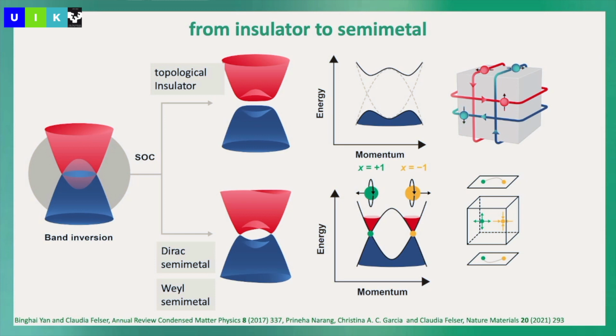And the relation is here: you could turn a Dirac semimetal into a Weyl semimetal by lifting the 4-fold degeneration into 2 times 2-fold degeneration, which you can see here. Then the bulk band structure would look like this. The nice thing is that you have these chiral crossing points in the electronic structure in Weyl semimetals, and therefore I like to draw it with these different colors because this excites me. Charlie already mentioned the chiral anomaly. So chirality in the bulk electronic structure, I think we can probably think even more about this, okay? Because here we have different phases of the Berry curvature at these different points, which is not the case in the Dirac semimetal. So we have chiral electrons in the bulk in this material, and this is why we can measure in Weyl semimetals this chiral anomaly.